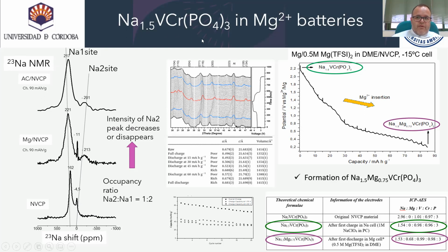The sodium 1.5 vanadium 1 chromium 1 PO4 3 sample was used for inserting magnesium at -15 degrees. The curve exhibits a fair discharge capacity reaching 90 mAh per gram. The compositions after chemical treatment and after insertion of magnesium were further checked by ICP analysis. So we can confirm the formation of sodium 1.5 and the insertion of 0.75 magnesium corresponding to this capacity.